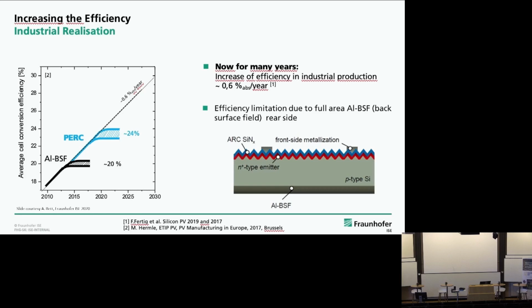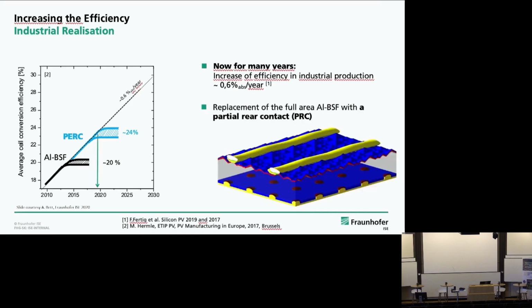The standard technology till about, I would say 10, 12 years ago is shown here. It's called aluminum back surface field. You have a P-type wafer, you have an aluminum backside contact, you make, of course, the anti-reflection coating, you make the screen-printed contacts, and finished is the old industry standard technology, which has a limit of about 20% of efficiency, which 20 years ago was a good number. Today, of course, we are no longer satisfied.